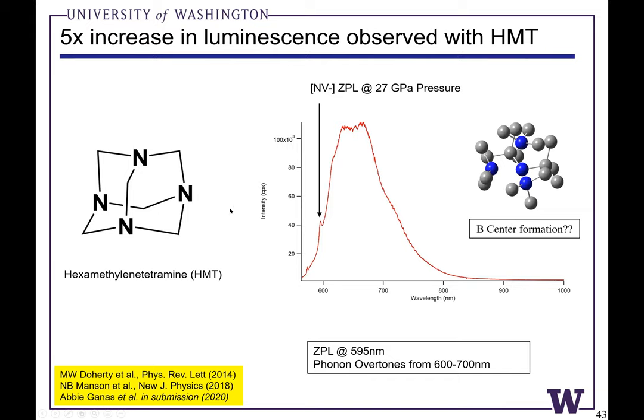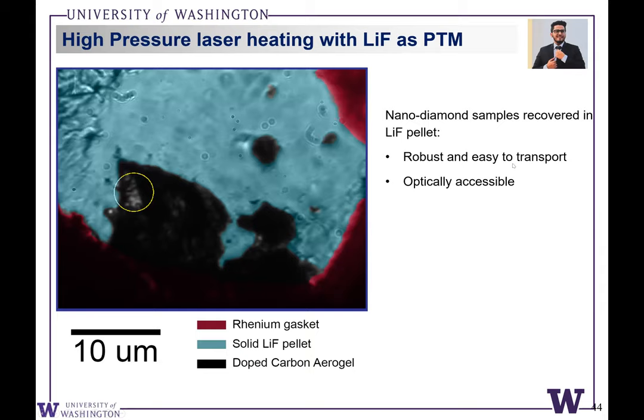One question we're currently trying to answer is whether we might be forming more complex defects. If you have this sort of tetrahedral configuration of nitrogen atoms in your starting molecule, we want to answer the question, can we observe the formation of the so-called B center, which is an array of four nitrogen atoms surrounding a vacancy in the cubic crystalline diamond lattice? Does the stereochemistry of the molecule that we're using to make these defects translate into the actual diamond crystals that we're making after our high-pressure laser heating experiment?